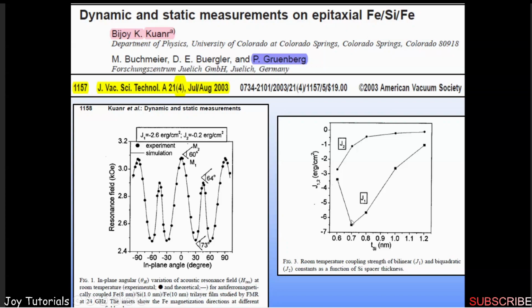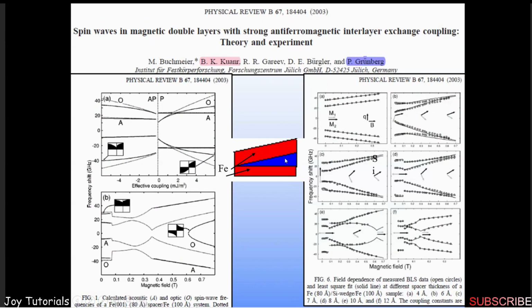What you can see here, the exchange coupling is the maximum when the silicon layer is at 0.7 nanometer, meaning 7 angstrom. This is the highest exchange coupling, thereby having the highest GMR value or TMR value. Here in this work, instead of a single layer, it is a wedge type of structure. This wedge type of structure is only for R&D, only for research, not for any device application, because in situ, one can see the exchange coupling of the GMR through Brillouin light scattering or the MOKE experiment, how much is the exchange coupling or how much is the GMR through different spacer layer.